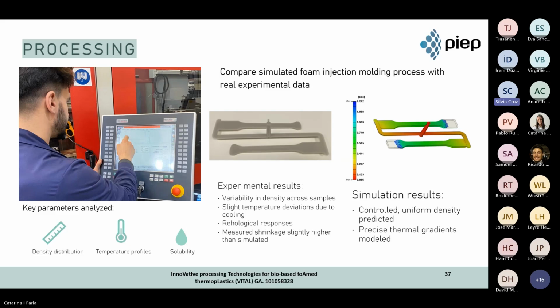In this slide, we present a comparison between simulation and experimental obtained results. On the left, we have the operator adjusting the parameters on real-time equipment, while on the right, we have the molded and simulated samples of the process with the material already characterized. We analyzed several parameters such as cell distribution, temperature profiles, material behavior during filling, and also the solubility of the gas in the polymer matrix.